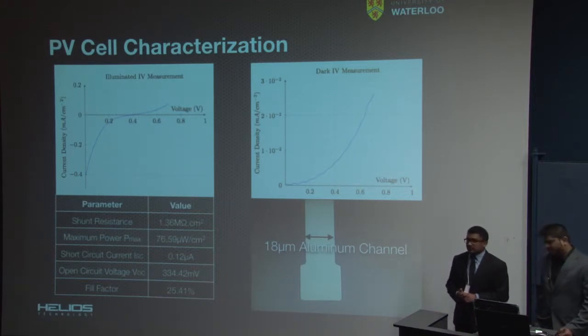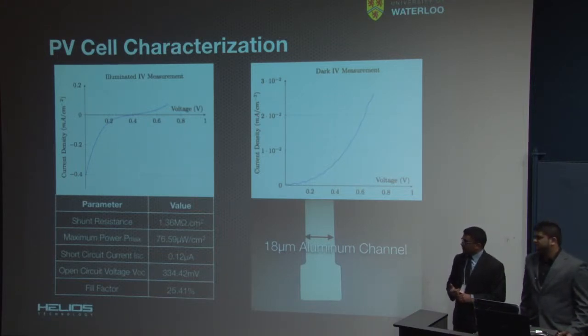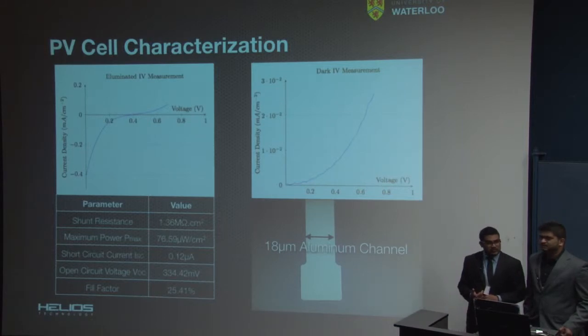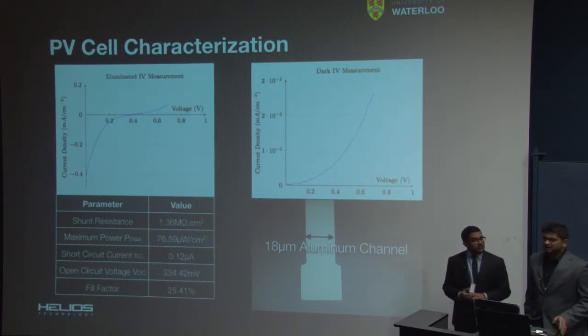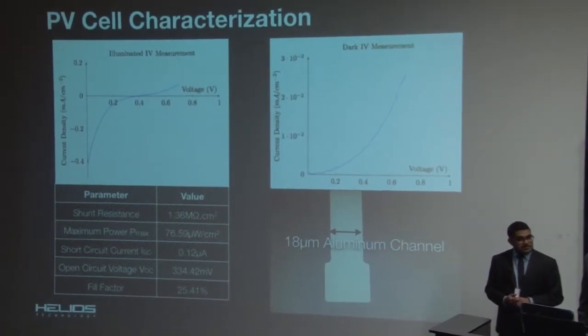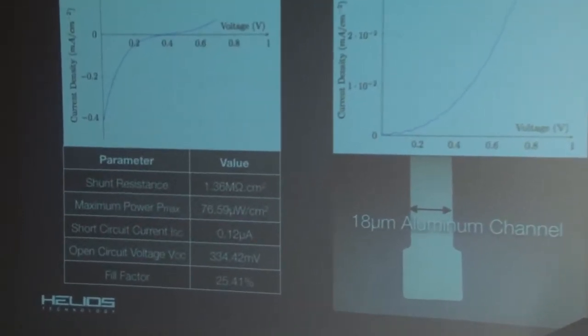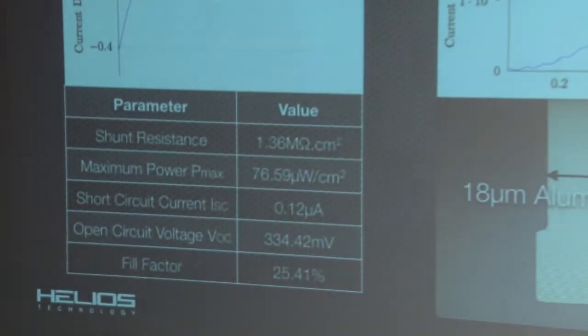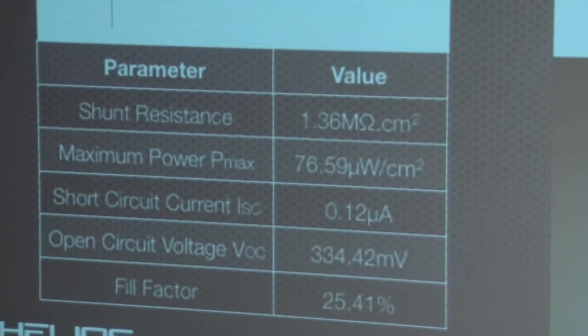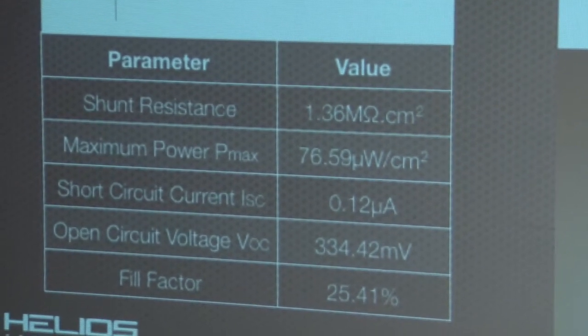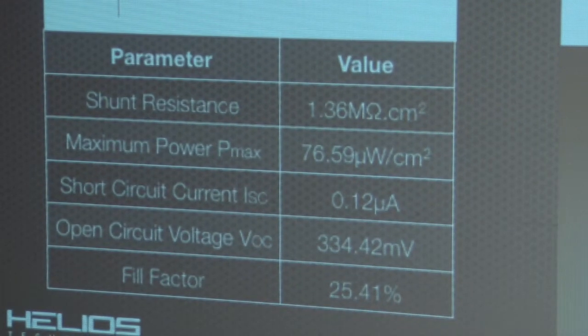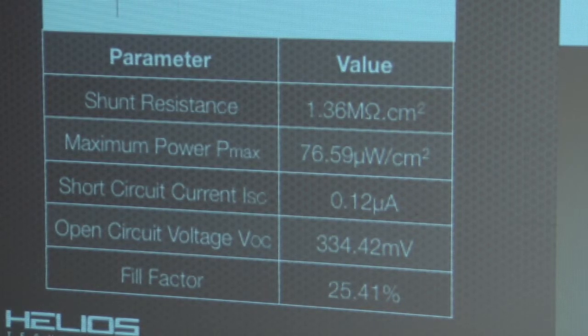And for our parameters of interest, we achieved a shunt resistance of about 1.36 megohms, which is ideal because a high shunt resistance allows for minimal internal current losses. And we also achieved a maximum power of about 76.6 microwatts per centimeter squared, which is again around what we expected.